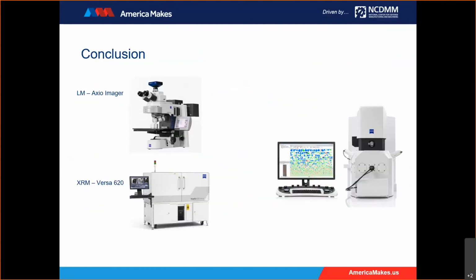So I hope that you've seen that characterizing additive manufactured powder is a task that requires multiple techniques and length scales to do it properly. In order to measure the particle size distribution for new or recycled powder, you can use light microscopes such as our Axio Imager. But if you're concerned about detecting contamination after recycling or your powder handling procedures, SEM like our EVO with SmartPI can be a useful tool to characterize your powder particles. And if you're doing alloy development or you want to look at internal porosity of your powder, you can use our Versa 620 for 3D reconstruction of the powder and even your final part.